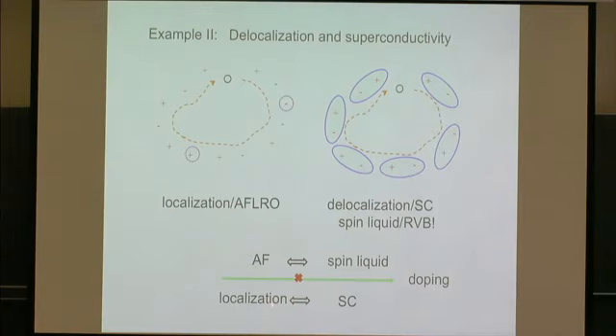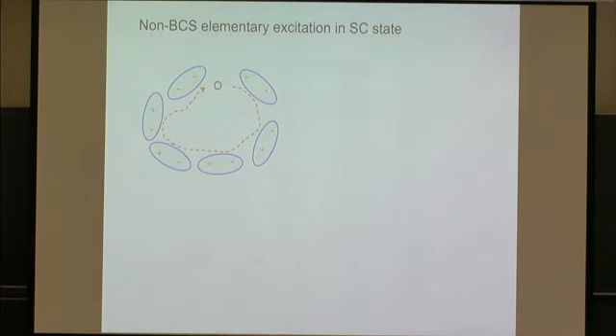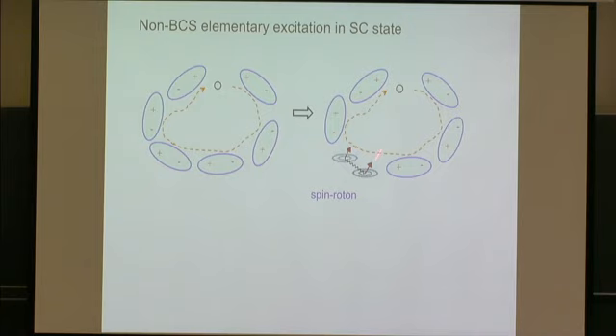In other words, when we have the localization-delocalization transition to superconductivity, the antiferromagnetic order will be driven into a spin liquid with short-range pairing. But there's a caveat here. We have to be careful. This doesn't necessarily tell you it's a superconducting phase, because for such a short-range paired spin liquid state, you can break up a spin pair to create spinon excitations. Once you have that at finite temperature, the condensed holes will see that through this non-local sign, and the condensate will not be happy with that. So in the end, they will form currents to screen this, to make the excited spins pair up. It's called a spin vortex, or vison.